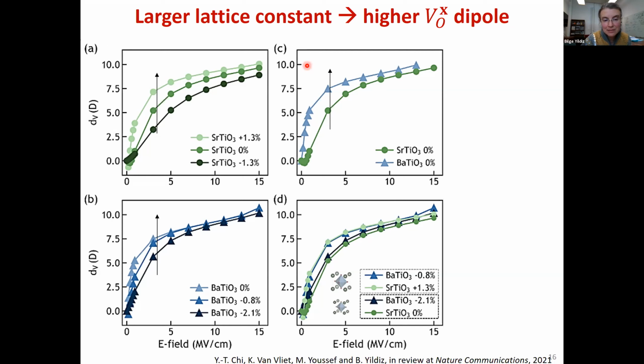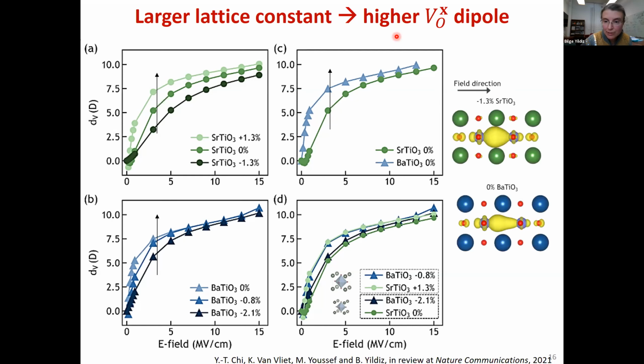So there is clear evidence here that as we keep the chemistry of the material very consistent, so stick to titanates, and only play with the lattice volume, we can strongly modulate the dipole, we can strongly modulate the polarization, again of these trapped electrons in the charge defect. Much stronger polarization, which we can see visually also, in the barium titanate compared to strontium titanate because the former has a larger lattice parameter.